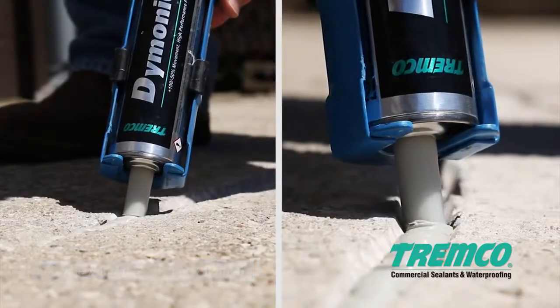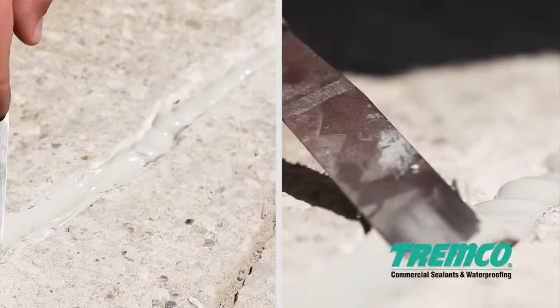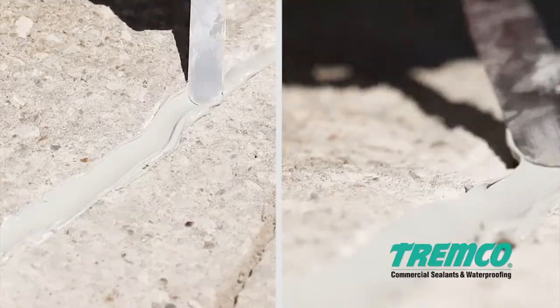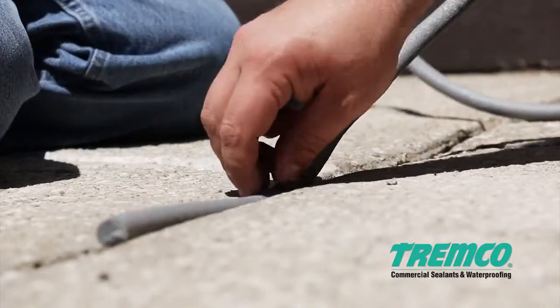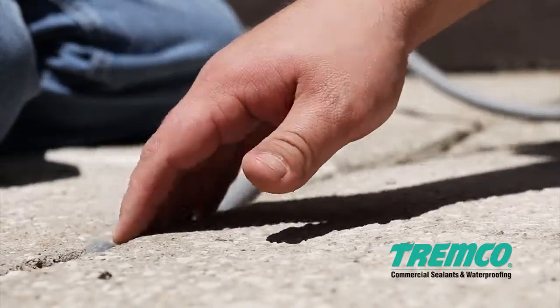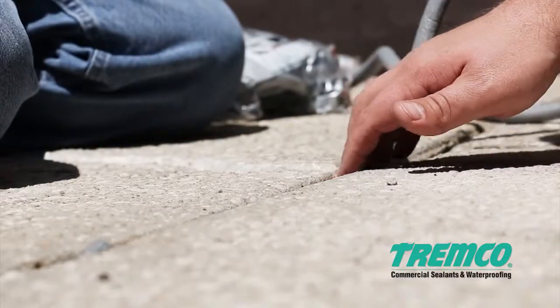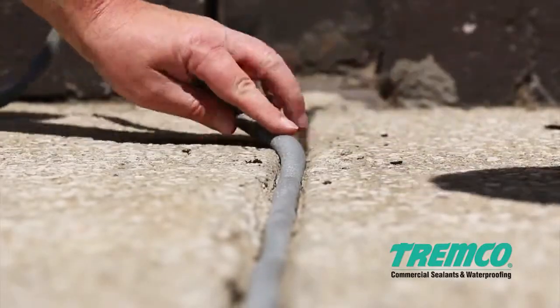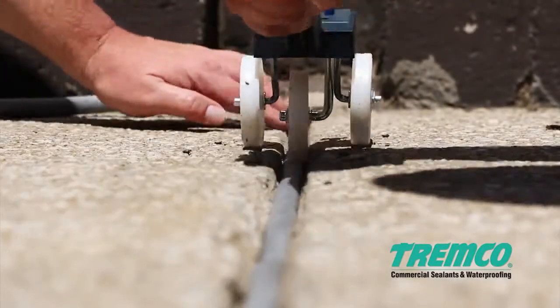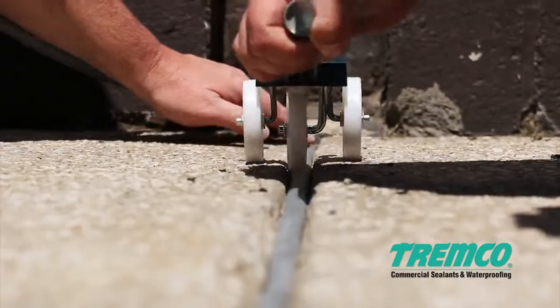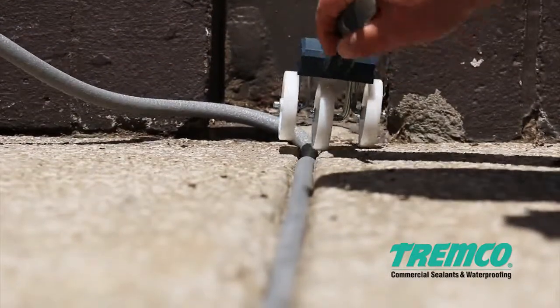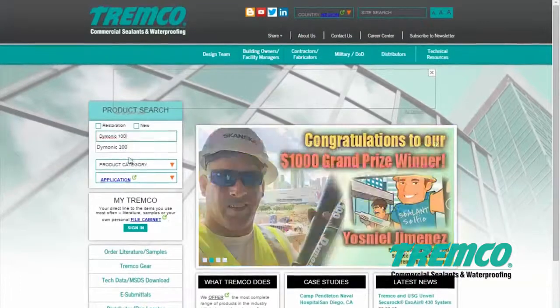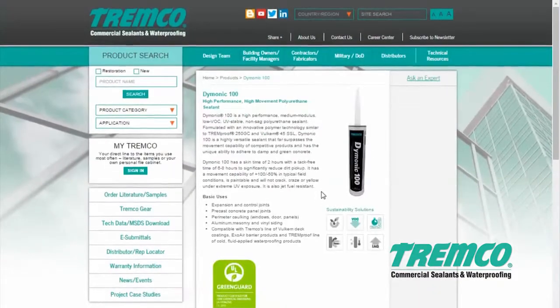Apply a bead of Dymonic 100 sealant in the crack and tool flush. For control joints, install a backer rod, 1/8 inch to 1/4 inch, 3 mm to 6 mm diameter, larger than the joint. Set depth of backer rod to control the depth of the sealant. Depth of sealant is measured from the top of the concrete surface. See Tremco application instructions for proper depth of sealant.